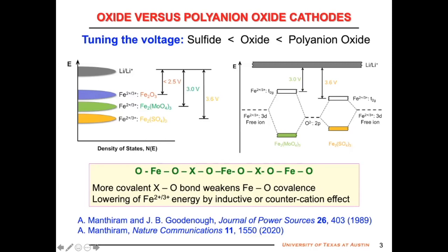you can increase the voltage even further in an oxide, because in these examples, for example, the FeO6 octahedra share corners with the XO4 tetrahedra, that is sulfate or molybdate or phosphate. So that means the oxygen is competing with both iron on one side and the X on the other side. So if the sulfur oxygen bond is very covalent, the iron oxygen bond will be less covalent or more ionic. Therefore, the iron redox energy will not be raised that much compared to in a simple oxide. So you increase the voltage.